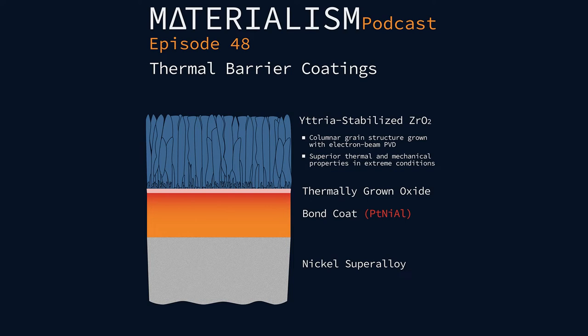We get these nice column structures that are separated by spaces, so you have a lot of convective heating that can occur in that area. At the same time, the material gets laid down with porosity. These are areas where heat is going to have to transport by the convective method, and thus you're going to be able to slow it down. So you get not only yttrium-stabilized zirconia, which has a pretty low thermal conductivity value for a ceramic. Oh yeah, it's not bad. Now it has a very porous structure. And combined with this columnar macro structure, you get a really fantastic material for reducing heat transport.